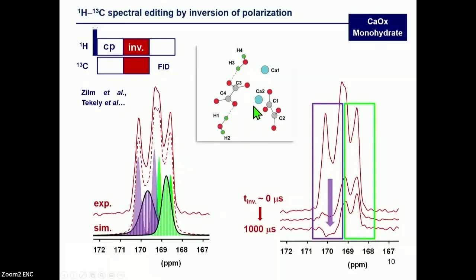Why? Because we know from the XRD data that the oxalates are connected to protons corresponding to the water molecules, but some molecules are closer to the proton than the other ones. So by editing, it will be possible to extract the chemical shifts corresponding to the carbon-13 which are more coupled to protons. And that's what we did here by increasing the inversion time. And you see that the whole deshielded part of the spectrum corresponding to the purple rectangle is inverting much, much faster than the other one in the green rectangle, meaning that the three purple peaks are closer to protons than the three green ones.